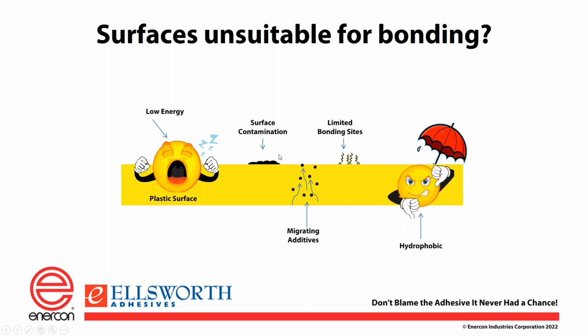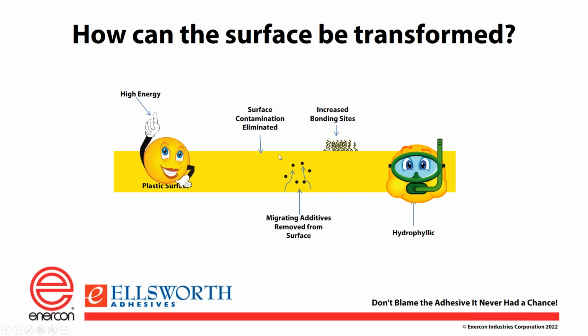So after our treatment, we go to the next slide, and hopefully we have a much higher surface energy. We'll go over that in a few minutes. We've removed contamination, increased the bond sites, and we've taken the additives away from the surface. And we've gone from a hydrophobic surface to a hydrophilic surface, and that is a much better prepared surface with which to bond.